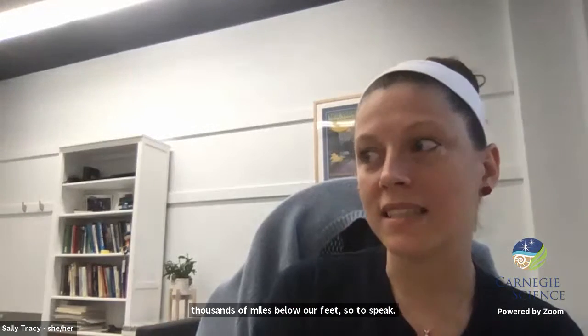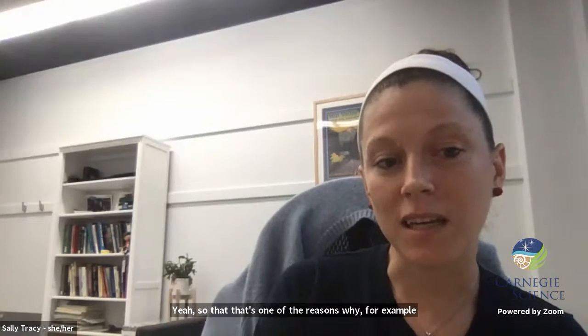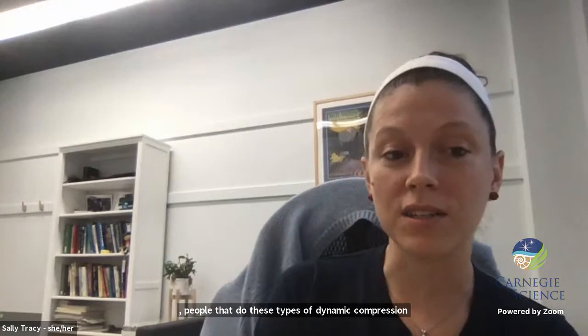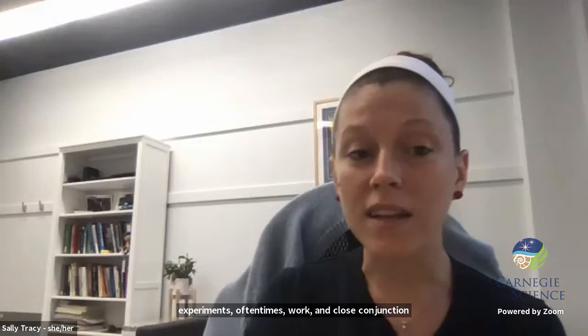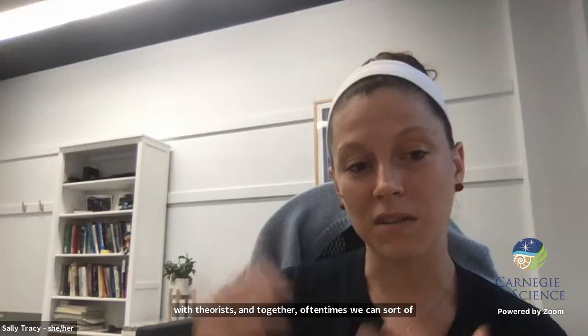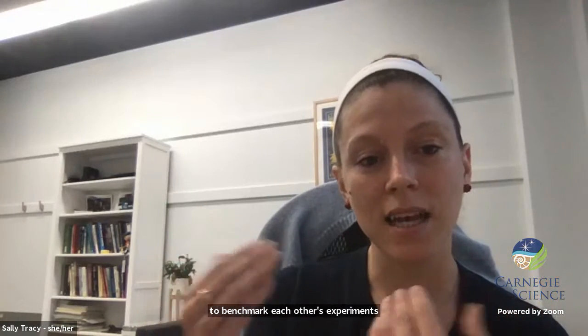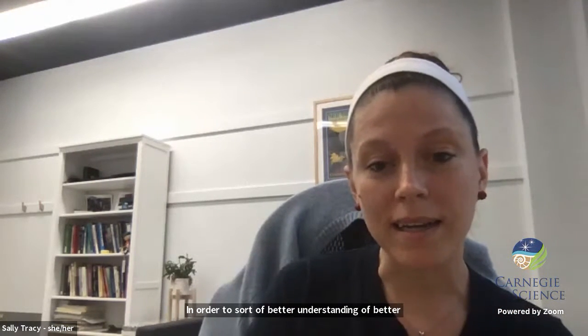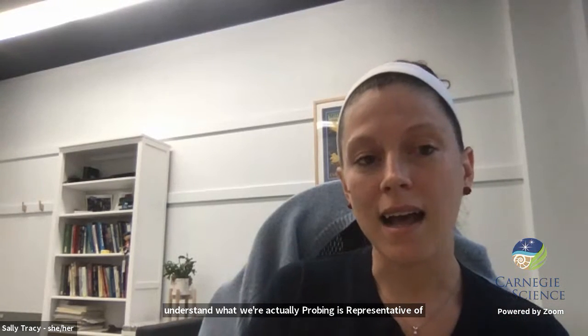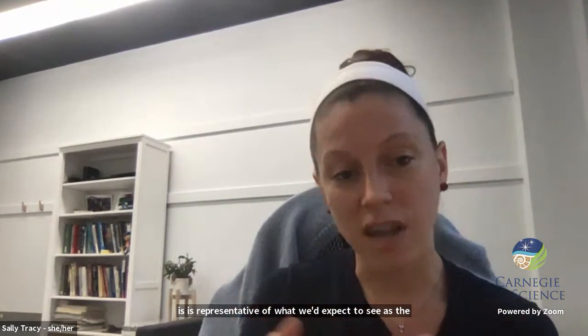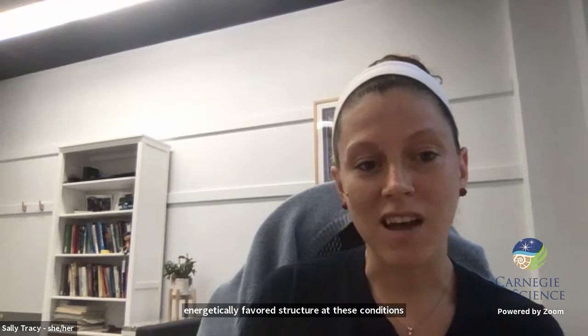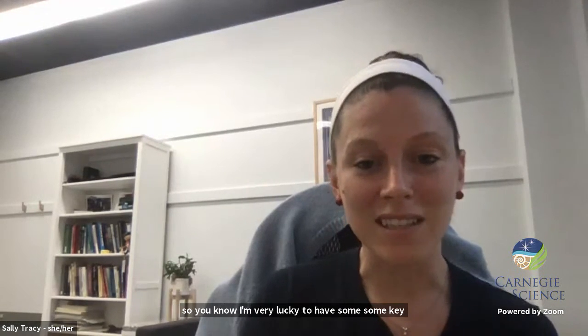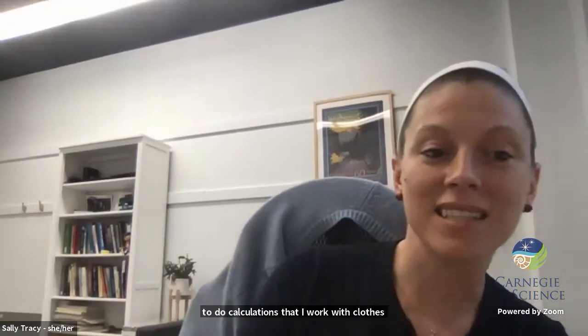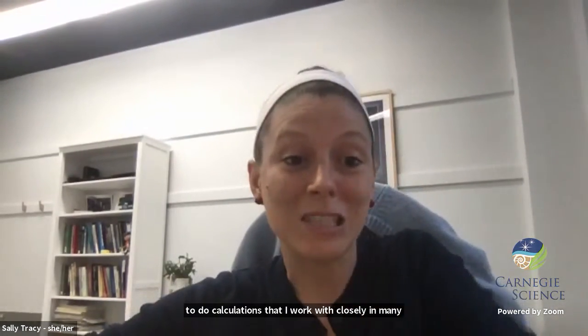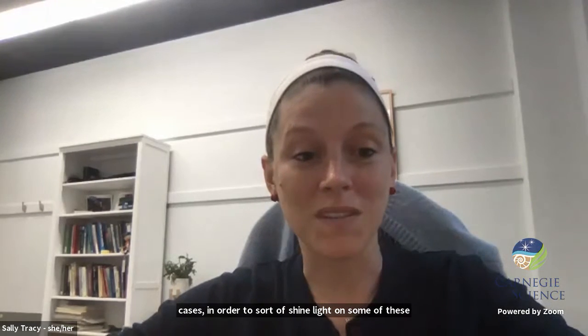Yeah, so that's one of the reasons why people that do these types of dynamic compression experiments often work in close conjunction with theorists. Together, we can serve to benchmark each other's experiments and calculations in order to better understand if what we're actually probing is representative of what we'd expect to see as the energetically favored structure at these conditions. I'm very lucky to have some colleagues that do calculations that I work with closely in many cases in order to shine light on some of these issues. And so that's another really important key element to these types of experiments.